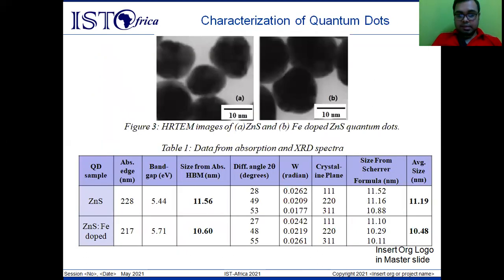And this is a HRTEM, that is high resolution transmission electron microscopy imaging of the fabricated quantum dots. You can see the size is around 10 nanometer, which confirms the formation of quantum dots. And the data obtained from the absorption as well as the XRD spectra is presented here. The approximate band gap is calculated from absorption using the hyperbolic band model, and from the XRD using the Scherrer formula. We can see that the average size of quantum dots approximated almost matches that of the actual size, that is in and around 10 to 11 nanometer.